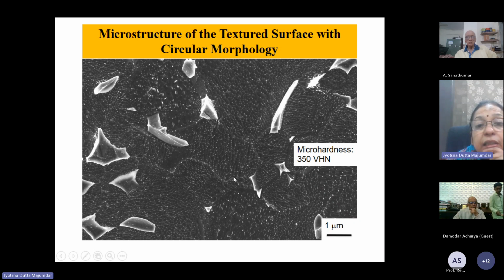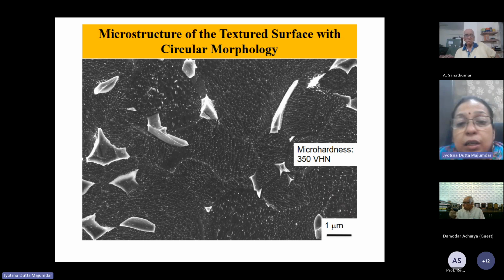We find that very small nanodots of oxygen were observed on the surface, and this kind of fine oxide is beneficial because, firstly, it improves the mechanical performance of the surface to a large extent in terms of wear and corrosion. And a second added advantage of the oxide formation is that it increases the bioactivity of the surface. Because on a titanium surface, whenever it is implanted, there is oxide formation which is spontaneous in nature. But that spontaneous oxide which forms on the surface is very loose and porous, so as a result it doesn't perform the way it should have performed.